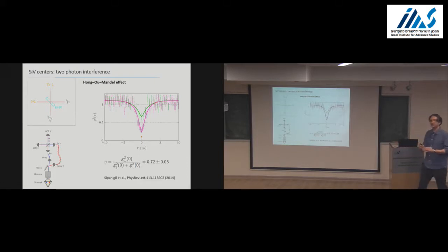So the photons emitted now by different atoms without any tuning are overlapping with high fidelity, and that's for a solid state system where you usually do have a disorder and atoms are not always the same. This is, I think, quite a remarkable property. The system is very stable, owing to the higher symmetry of these color centers, so they do not get perturbed by local electric fields.